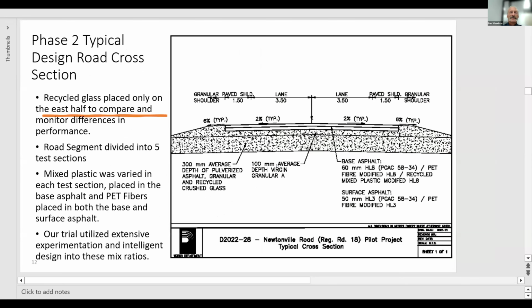Here's our typical design road cross-section. The recycled glass was placed only on the east half to compare and monitor the differences in performance. The road segment was divided into 5 test sections. The mixed plastic was varied in each test section. It was placed in the base asphalt. The PET fibers were placed in both the base and the surface asphalt.